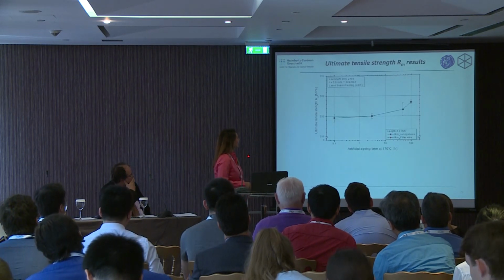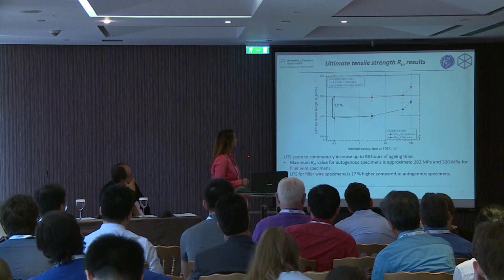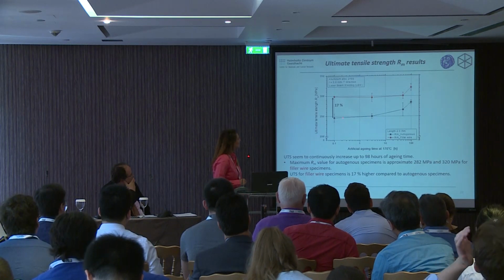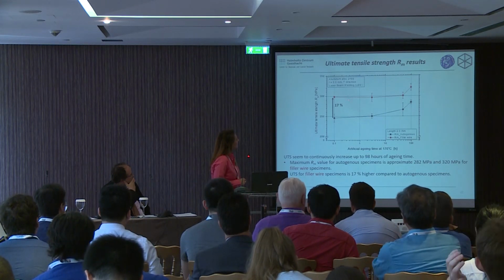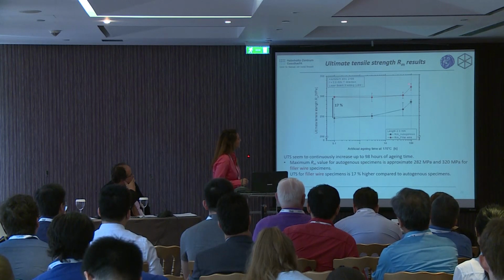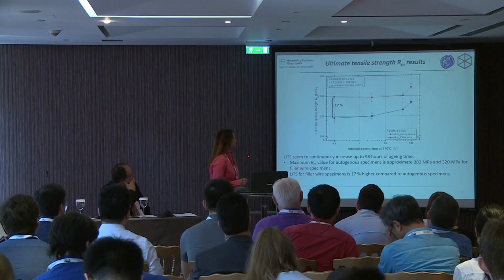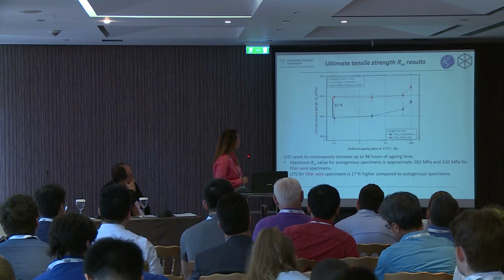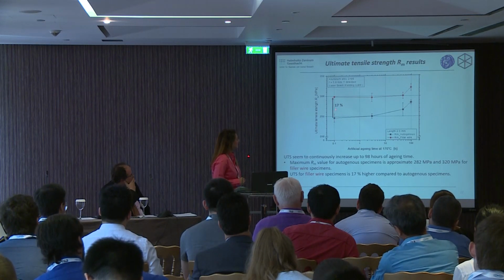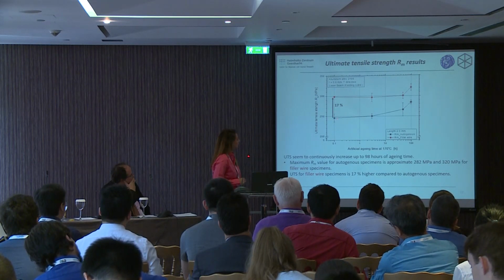Ultimate tensile strength versus artificial aging time. We can see that in both cases we have a continuous increase up to 98 hours. Ultimate tensile strength for filler wire specimens is 17% higher compared to autogenous specimens.